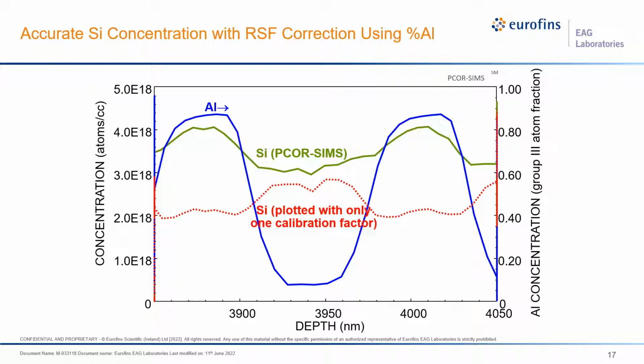This slide shows the silicon doping profile in an N-type DBR using only gallium arsenide sensitivity for silicon, that's the red curve, and with the P-core SIMS corrections applied, that's the green curve. As expected, where the aluminum content is low, the two curves are close together, and that's showing that there's not really much error in using only the gallium arsenide sensitivity factor. However, in the DBR layers with very high aluminum content, the difference between the two curves is very significant indeed. In fact, without the P-core SIMS correction, the silicon profile would lead one to believe that there is actually more silicon in the low aluminum layers than in the high aluminum layers, which is actually the opposite of what is actually occurring. You can see how important the P-core SIMS correction really is.